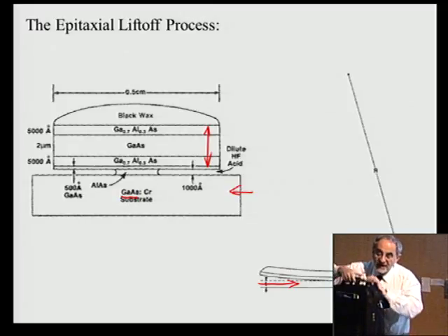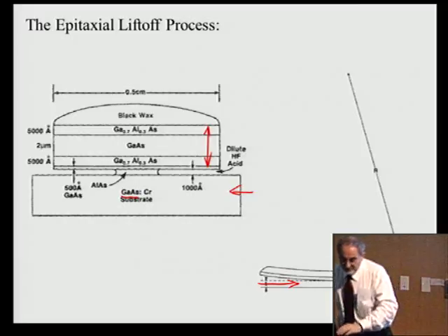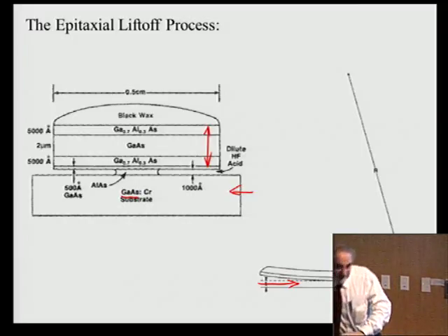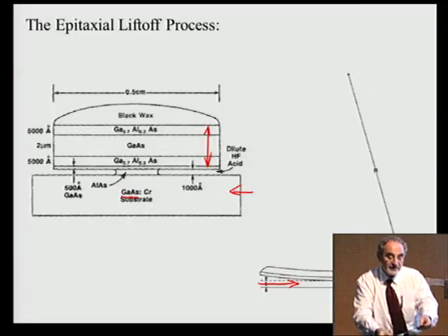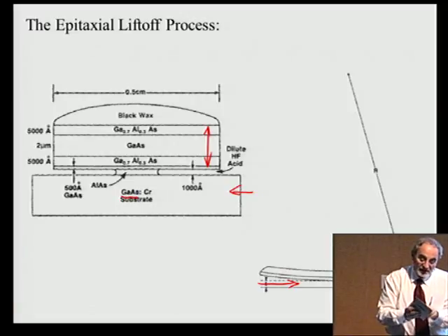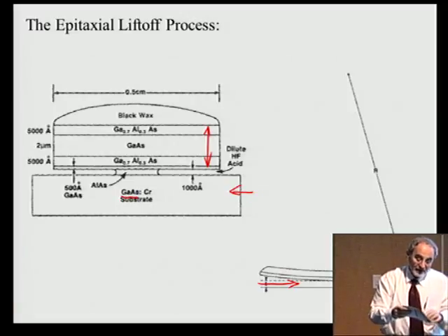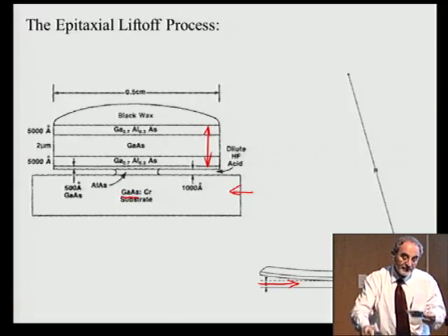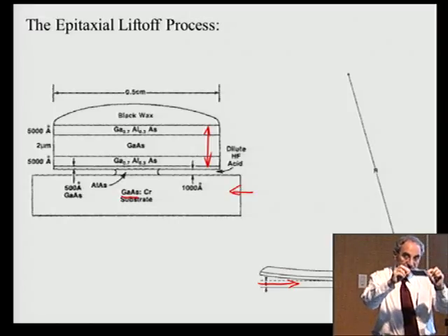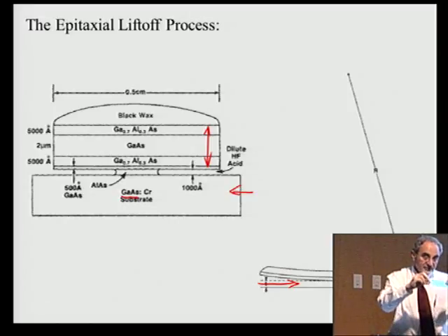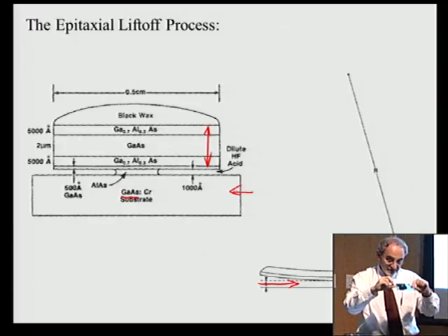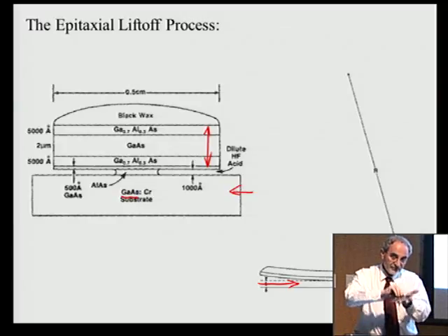Okay, so these are the actual solar cells that broke the world's record, and that also project out to be very, very low in cost. We peel them from a 6-inch wafer, and this is exactly how it comes out. This is epi single crystal gallium arsenide of the highest quality. It is peeled from the substrate.